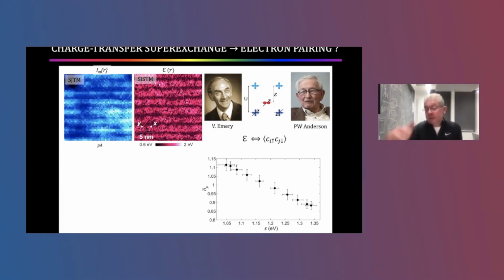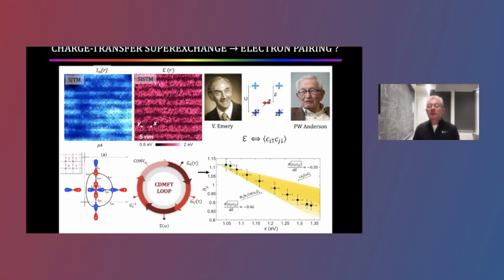Now, this is a fact in and of itself, but if you're willing to stipulate to the three-band Emery model and its DMFT solution, then the measured relationship between pair density and charge transfer energy is in excellent agreement with the theoretical predicted relationship for charge transfer superexchange being the mechanism of high temperature superconductivity.